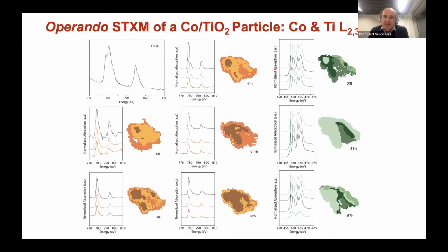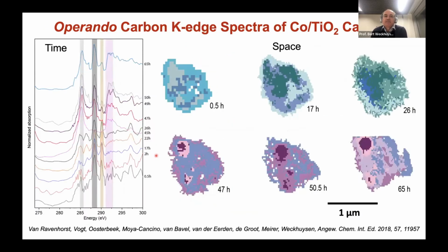But before showing that, I first want to show you, you can measure cobalt and titania, time resolved, 0, 19 hours, 41, 51, 69, and the same holds for the titania. And you can do that spatially resolved. For example, here I show you principal component analysis, where you see certain spectra depending on a certain catalyst particle. So you see differences in the different metal nanoparticles as function of time.